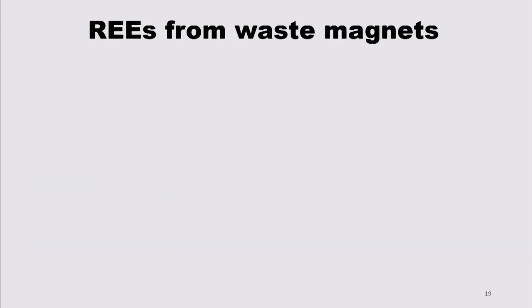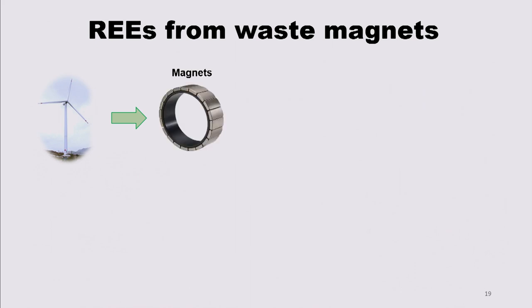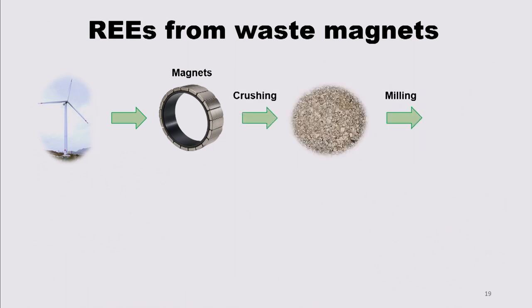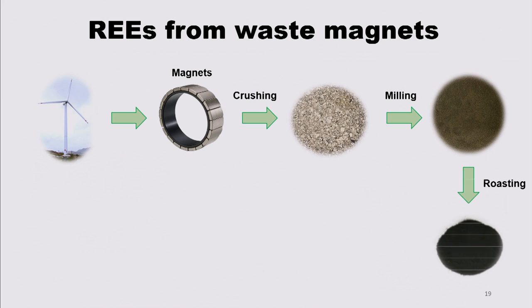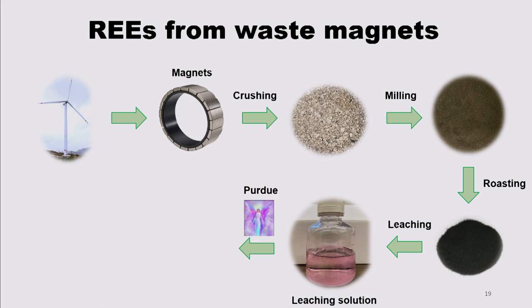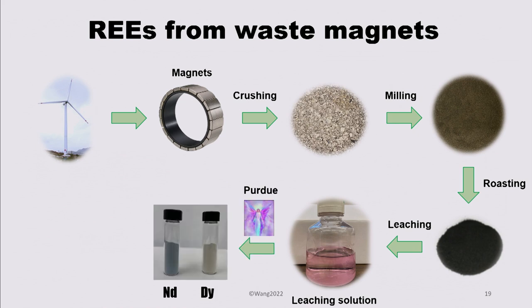So this example was for the wind turbine motor at the end of life. We collect them, crush them into small particles, mill them, oxidize and roast them into oxides, and leach with a weak acid into a leaching solution, and that solution was purified using the chromatography methods into high purity rare earth, and then that can be made into magnets.